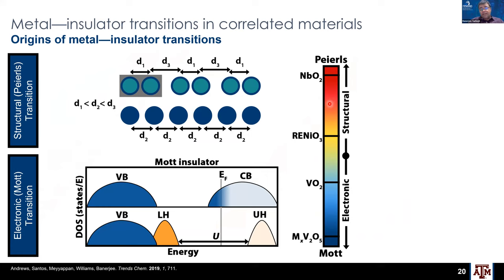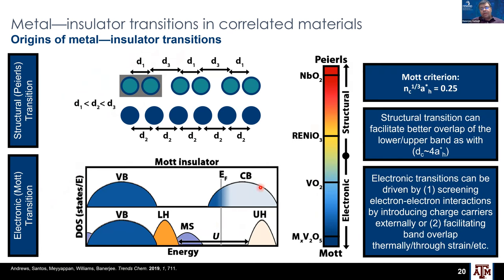transition. And it does have a substantial component, oftentimes, that has to do with de-pairing of vanadium dimers along a one-directional chain. And so there is a substantial structural component to it. And again, what we're aiming for is something that is almost entirely a Mott transition, where we can get a large change in conductivity, but we can drive this using charge injection or by facilitating band overlap, and so with relatively minimal lattice changes going on.